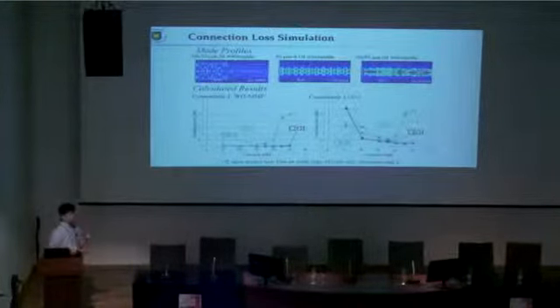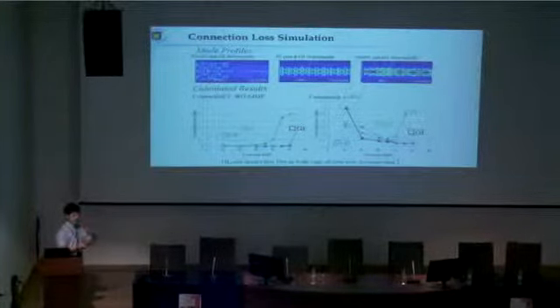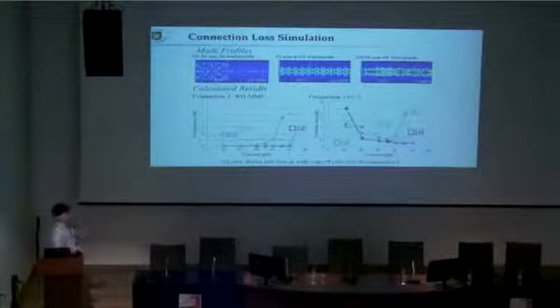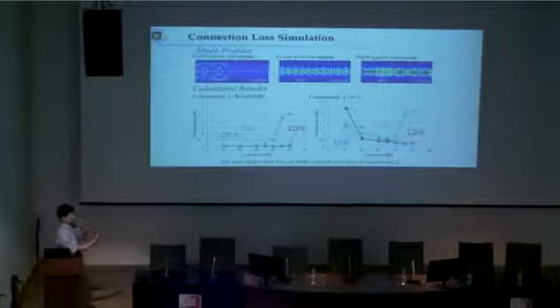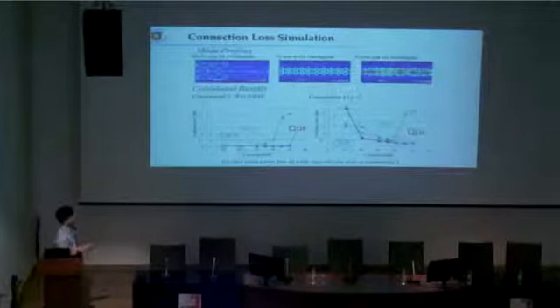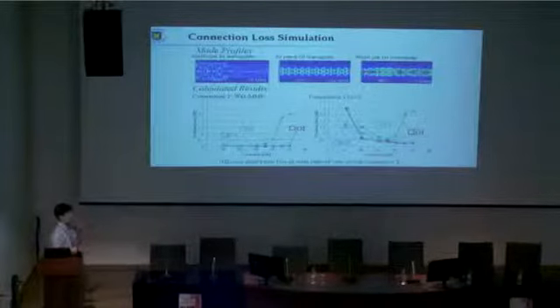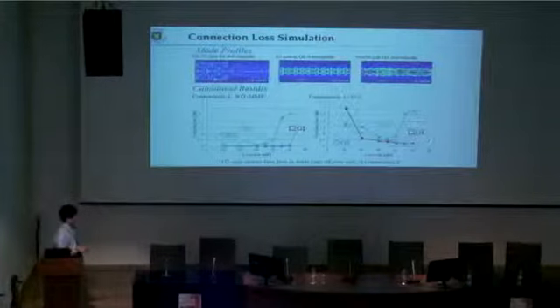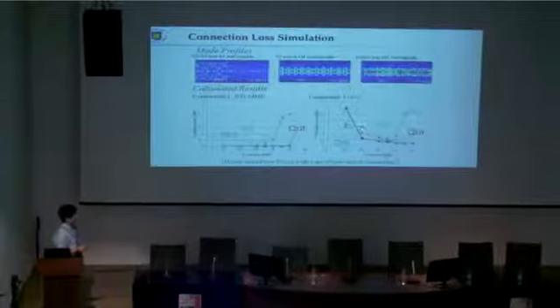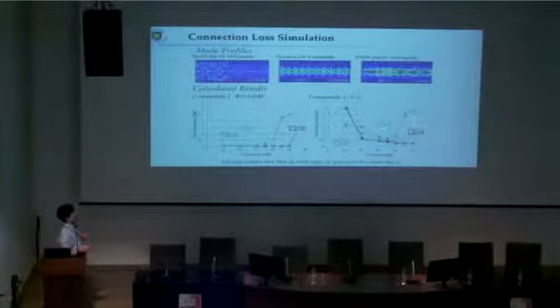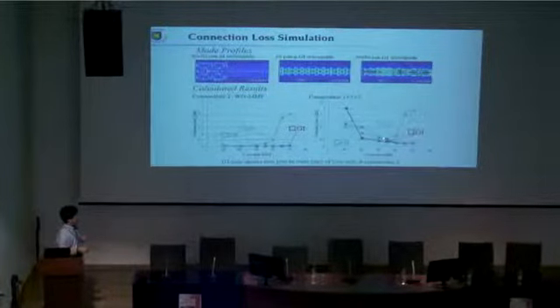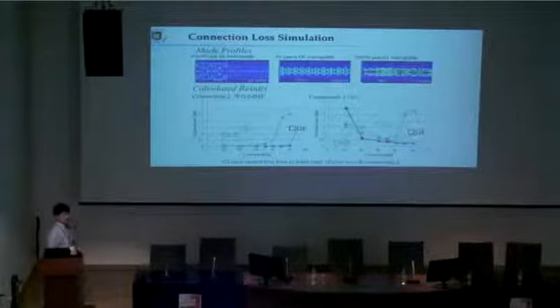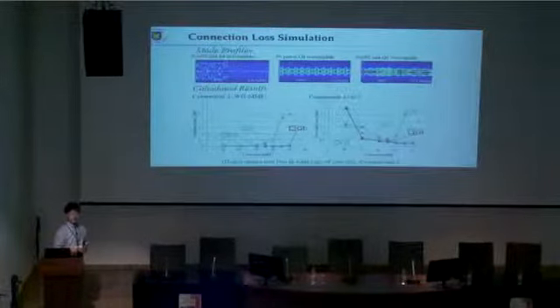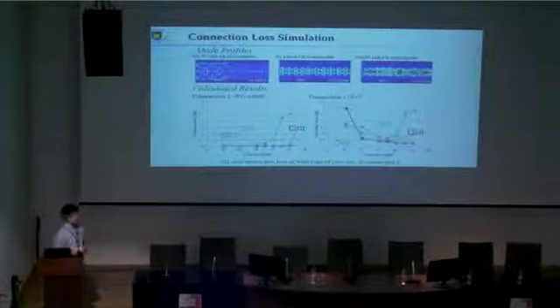On the other hand, because we are supposing multiple connections between the waveguide, fiber, and waveguide, there are three connection points. From the light source to the waveguide is connection point 1, the second is here, and the third is again from the fiber to the waveguide. In this case, GI circular core is not the optimum because of the modal field mismatching, while square core GI shows a wide tolerance in core size, while step index square core shows the lowest coupling loss when the core size is 30 to 35 micron. Therefore, from this result, we started our research to fabricate a graded index core multimode waveguide.